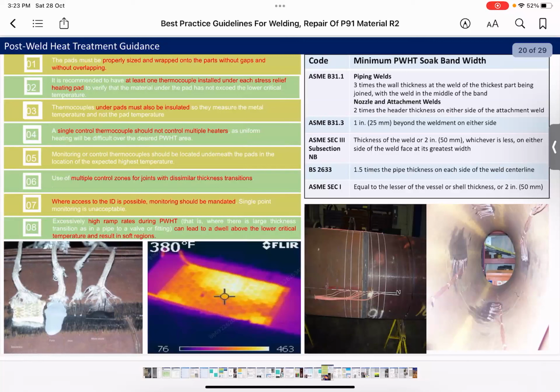We are doing the heat treatment very close to the transformation temperature or AC1 temperature, and many factors can affect the accuracy of the post-weld heat treatment. If the temperature goes slightly above the specified temperature, we might exceed the lower critical temperature or AC1 temperature, resulting in cracks during service. So the points are that the insulation pads must be properly sized and without gaps and without overlapping. At least one thermocouple installed under each stress relief heating pad. A single control thermocouple should not control multiple heaters, and multiple control zones for joints with dissimilar thickness transition.